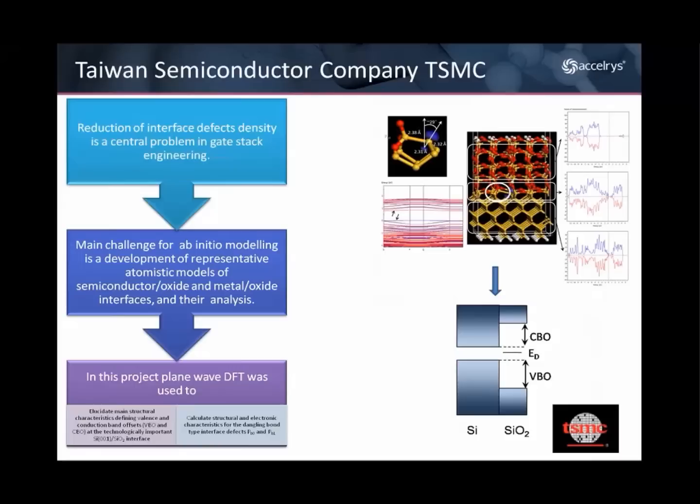We think about a company like a semiconductor like Taiwan Semi. These people spend a lot of time trying to understand interfacial regions. I remember once talking to someone about amorphous silicon, and they asked me a very simple question. They said, Michael, how many atoms do I have to move before I can't tell it's crystalline, before I actually see it as an amorphous material? Is it 10? Is it 20? Is it in a cluster? What happens if I do it? And so we just spent some time literally simulating electron diffraction and X-ray scattering patterns, starting with a crystalline lattice and then randomly removing or moving, two sets of experiments, different percentages and different distributions of atoms, till we basically, with the resolution instruments available at that point, couldn't tell.